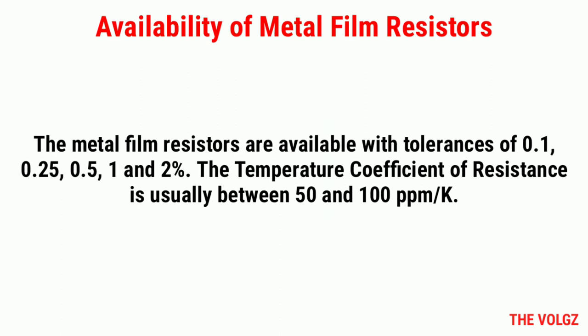Availability of metal film resistors. The metal film resistors are available with tolerances of 0.1%, 0.25%, 0.5%, 1%, and 2%. The temperature coefficient of resistance is usually between 50 and 100 ppm/K.